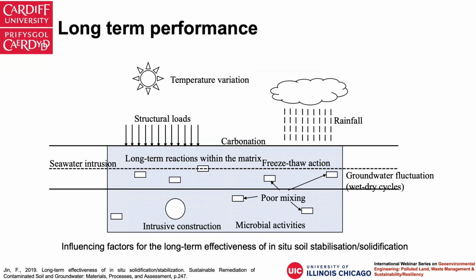Apart from these pros and cons, in terms of long-term performance, Portland cement also has a lot of uncertainties associated. We all know that portlandite, or calcium hydroxide, has very high solubility, so under rainfall, it tends to be leached out. And it also has a high tendency to be carbonated under ambient carbonation conditions. So these will all degrade the Portland cement. And there are lots of other factors such as seawater intrusion, freeze-thaw and wet-dry cycles, as well as microbial activities. All of these are under-researched at the moment, and there's very little field data to support the satisfactory long-term performance of PC-based soil stabilization solidification.